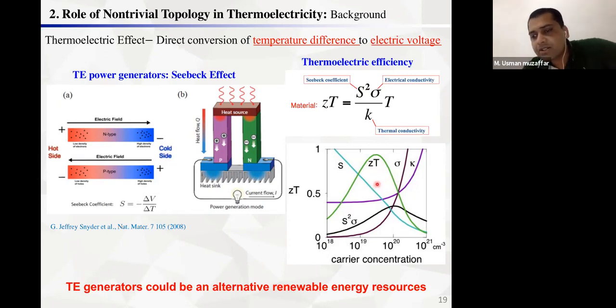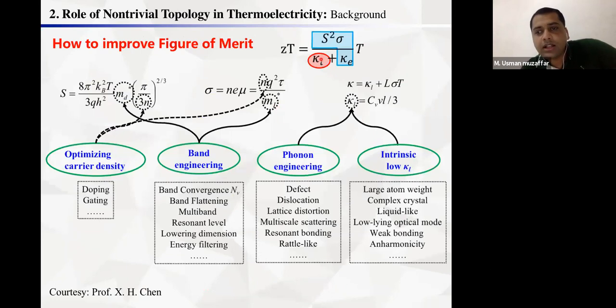On the other hand, when we talk about the thermal conductivity, which is directly proportional to the carrier concentration, with the increase of the carrier concentration, the thermal conductivity also increases. So we need to increase this factor, and need to decrease this factor. But they are all interconnected with each other. So then how can we decouple these parameters from each other?